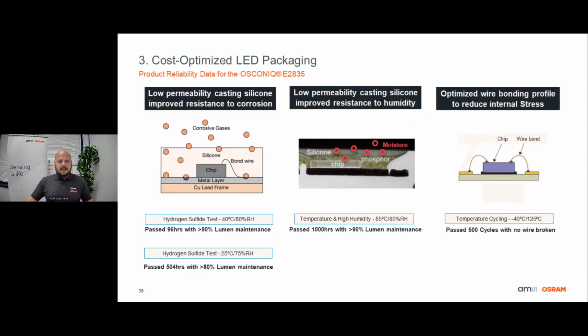Now, when you select LED components for your fixtures, it is crucial that you select LEDs that have gone through industry standard tests for hydrogen sulfide, humidity, and temperature cycling. Here we can see that by incorporating all the advancements that I had just previously mentioned, we have enabled the OSCONIQ E2835 to pass these industry standard tests. Many low-cost lead frame LEDs available in the market were not developed with these conditions in mind and may fail the test. So that is something that can be considered when you are looking at LEDs like this.